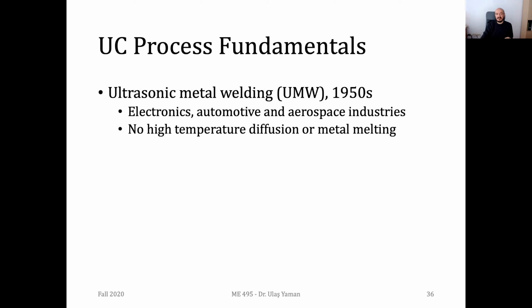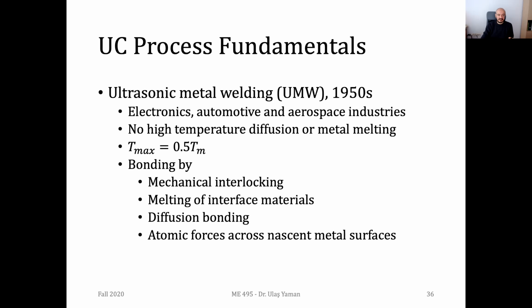Since if you have high temperatures, probably you're going to damage the electronic components, but if you just have an ultrasonic vibration or ultrasonic welding process, you will not have high temperatures. And the maximum temperatures in this process are usually about half of the melting point temperature of the material, or usually less than that. And in this welding process, the bonding is obtained by mechanical interlocking. The parts will go inside each other, or if you have interface materials, they will be melted and joined together, or you might have some plastic deformation and diffusion may happen, or atomic forces across your nascent metal surfaces may help you join these sheet metals together.